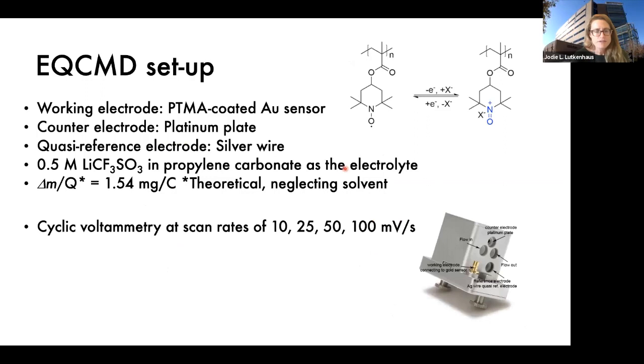Okay, so for the setup, we have a 3 electrode cell, but it's all encompassed around this QCMD crystal. The working electrode is our PTMA-coated gold QCMD sensor, and the counter electrode is a platinum plate. We have a quasi-reference electrode, which is silver wire. We can later calibrate it with ferrocene to estimate the potential that we observed. The electrolyte is 0.5 molar lithium triflate in propylene carbonate. And then again, this is the theoretical delta M over Q we're expecting. And then we just do cyclic voltammetry for this experiment.